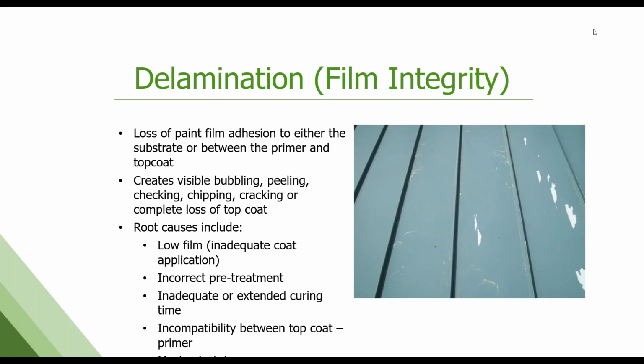Delamination, or lack of film integrity. So this is when the paint is coming off for some reason. This is a really tough one to troubleshoot out in the field because it can have a multitude of root causes. It creates a visible bubbling or peeling of the paint. Sometimes it's between the top coat and the primer. Sometimes it's all the way down to the substrate. The most common reasons for this are low film during the application process, incorrect pretreatment being used on the strip, maybe the curing time of the paint wasn't right, or an incompatibility between top coat and primer.